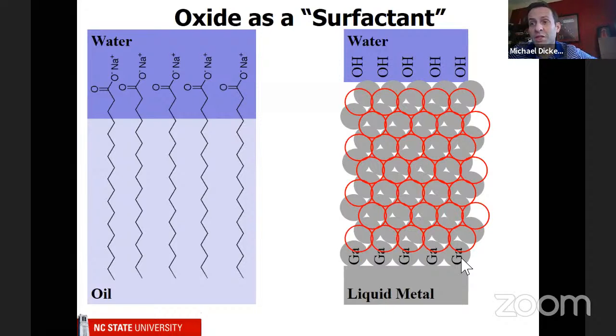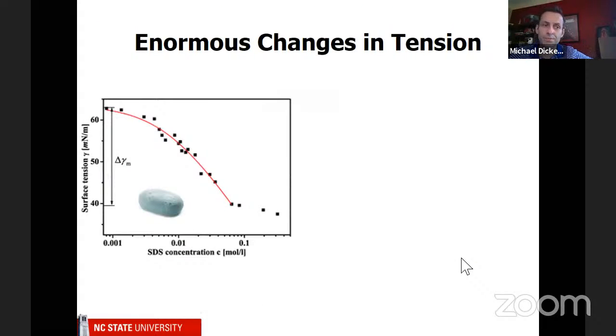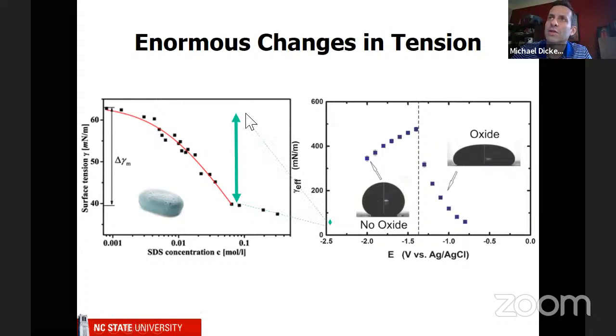Now, to give you an appreciation for how big the changes that we're getting in tension are, look at this plot of surface tension of water. Remember, water is about 72, so it's up here. And if you start adding soap, which is called SDS, sodium dodecyl sulfate, this is a log scale, you'll see that the surface tension will drop, but at some point it doesn't drop anymore. And that's because the surface is completely covered with these surfactant molecules. Anyway, if you put that delta from 70 to 40 on our plot, it's this little point here. It's really cute. It's nice and little. That's what soap does. In our case, remember, we're going from 500 down to almost 0.